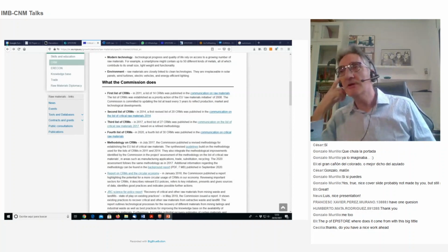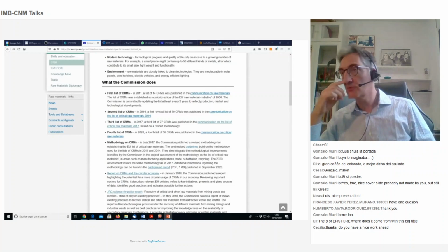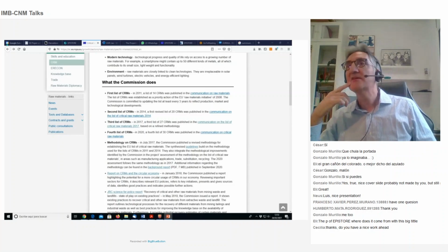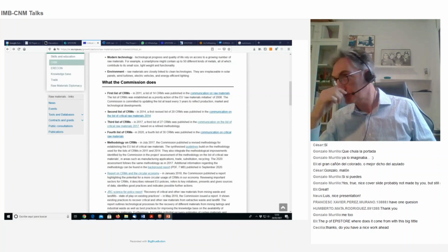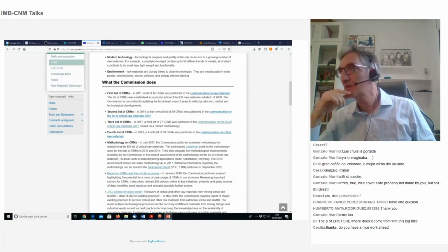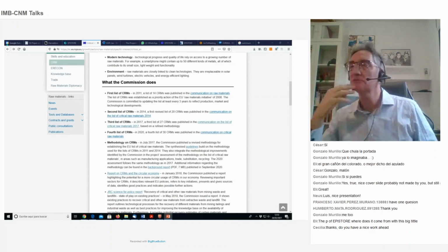In principle, the silicon itself should not be under stress, because it will be crystalline silicon in the end. But it's true that once you start to put on top those other materials, then stress can build up. Indeed, we know from previous experiences with stacks of materials on top of silicon nitride membranes that the overall stress is compressive, so they tend to corrugate or to buckle.